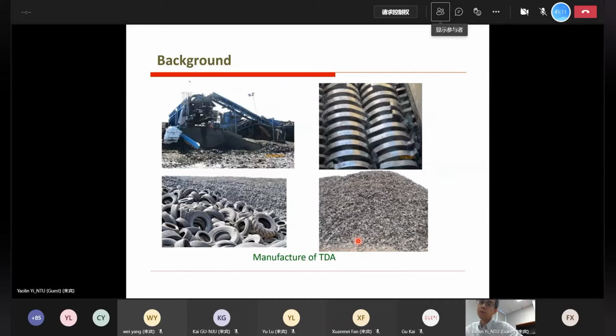How to produce TDA? Actually very simple. Just cut the discarded tire into small pieces. But if you want a finer size, for example, if you want to make it a smaller size, it costs more. What we can sense is that there are large voids between these tire pieces, because they are made from rubber, and the rubber is easy to deform.